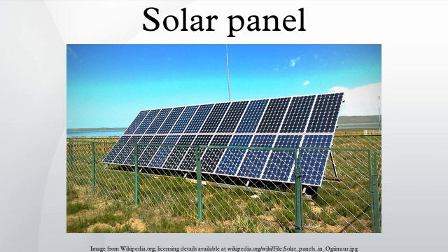Recycling: most parts of a solar module can be recycled, including up to 97% of certain semiconductor materials or the glass, as well as large amounts of ferrous and non-ferrous metals. Some private companies and non-profit organizations are currently engaged in take-back and recycling operations for end-of-life modules. Recycling possibilities depend on the kind of technology used in the modules. Silicon-based modules, aluminum frames and junction boxes are dismantled manually at the beginning of the process. The module is then crushed in a mill and the different fractions are separated: glass, plastics and metals. It is possible to recover more than 80% of the incoming weight.